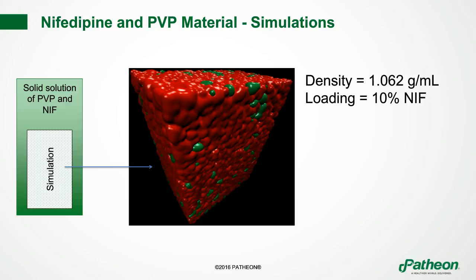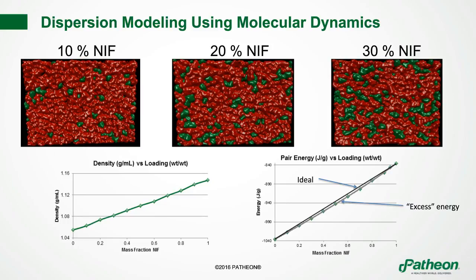So on the next slide, and I'll take some time to go through this, you see different loadings of drug and polymer. Now, the first thing to notice is as you go from the left to the right, you've got 10% nifedipine, 20% in the middle, and 30% by weight nifedipine in PVP. Now, the 10% looks very similar to the previous slide where you've essentially got a true dispersion. You've got drugs that are basically individually spaced within the polymer matrix, and this is all an amorphous matrix, such that the drugs would be released very, very rapidly and effectively.